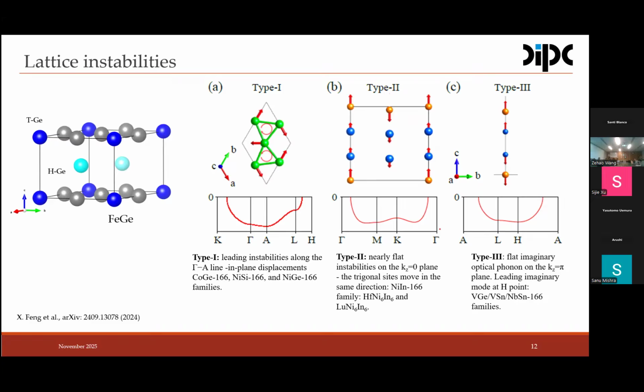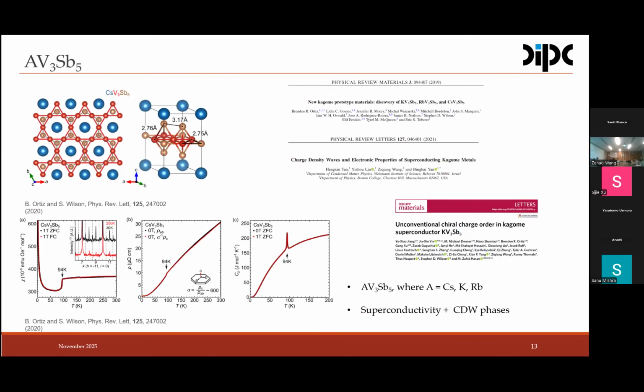So in this talk, I will mostly focus on the type 3 charge density waves, which indeed, for the case of ScV6Sn6, happens to have the same electronic structure as the 135, CsV3Sb5. This is the first Kagome metal, as far as I know, reported so far. It has a charge density wave around 94 Kelvin, with a peak in the specific heat. There are a lot of reports and a lot of controversy about the low temperature phase of the charge order. It's a multi-Q charge density wave with propagation vectors connecting the M and L points of the Brillouin zone.